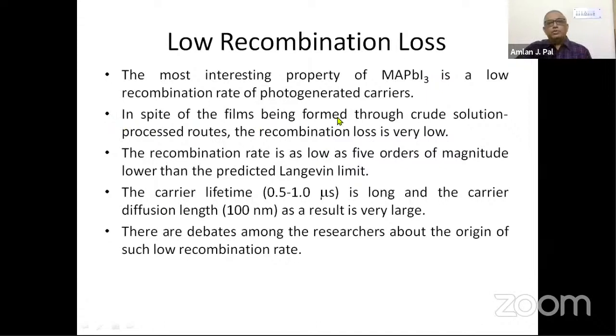In spite of the films being formed through a crude solution process route, the recombination loss is very low, because it's not any high vacuum or ultra clean environment that we use. You just make it by the spin coating method, still you find that the recombination loss is low. It is as low as 5 orders of magnitude lower than the predicted Langevin limit. And the carrier lifetime is long, and the carrier diffusion length is large because of that.